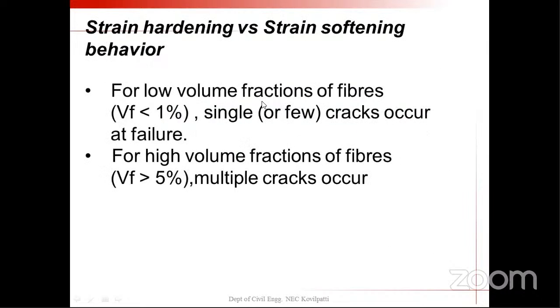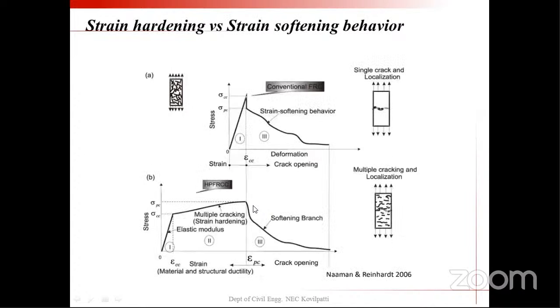So this is the point I mentioned. With a low volume fraction, only single cracks may occur, that is strain softening. With a high volume fraction, more than 5%, multiple cracks occur, that's strain hardening. So this is a strain softening and strain hardening diagram. In the first diagram, you can even see the x-axis is not the same in both diagrams. Here it is deformation versus stress. Here it is strain versus stress.